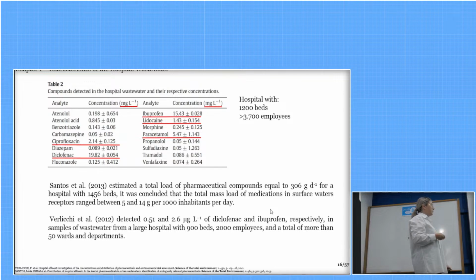Then we investigated in the literature for similar reports, where Santos showed that it is common for a load of 306 grams per day total of pharmaceuticals to be discharged by a hospital with almost 1,500 beds. And by Verlicchi, the amounts of 0.51 and 2.6 microgram per liter for diclofenac and ibuprofen. And here, the samples were collected from a hospital with 1,200 beds with over 3,700 employees. So the results are consistent and they worry because of the high concentrations for these 6 pharmaceutical substances in addition to the presence of all these others.